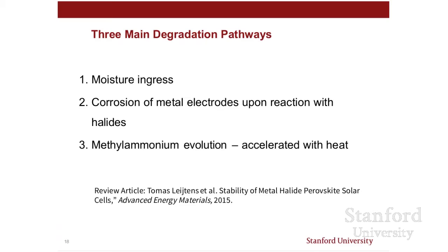Another one, it turns out the halogens, that's the iodine or the bromine, move around very easily, and they can react with metal, especially silver. But I'll show you in a slide or two how to avoid that problem. And finally, methyl ammonium can leave the film relatively easily. It'll slowly come out at 80 degrees, and by the time you're at 100, 110 degrees, it will come out very quickly. And that could be a problem for field use where the temperature might hit 80 degrees C, but it's also a problem in manufacturing where sometimes you might have a processing step at, say, 130 degrees.